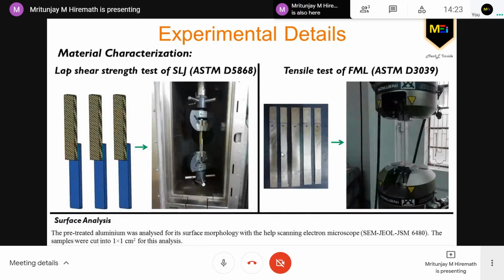The next step was to characterize the material. The specific characterization, like the lap shear strength test, was carried out for the single lap joint. This was carried out to evaluate the bond quality existing between the aluminium and the glass epoxy composite, and was conducted with respect to ASTM standard 5868. This was conducted in a universal tensile test machine, as you can see in the picture over here.